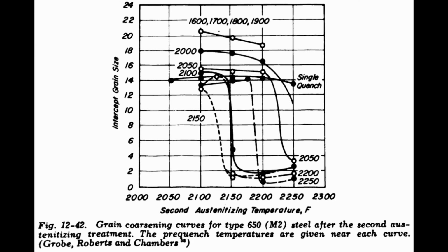So there were studies done a long time ago, I think in the 60s, where they were exploring something called fish scale grain. And when they looked at these high alloy steels, if they would austenitize them twice, like they would austenitize one time from a high temperature and then quench, and then they would decide they needed to do it again for whatever reason, they would get a lot of grain coarsening and the grain size would get really large. So they did a big study on this, and they found that if they used low initial austenitizing temperatures, that they would get a refinement in grain size when they followed it up by a more normal second austenitizing temperature. So grain refinement is apparently possible, and this might help with our toughness.